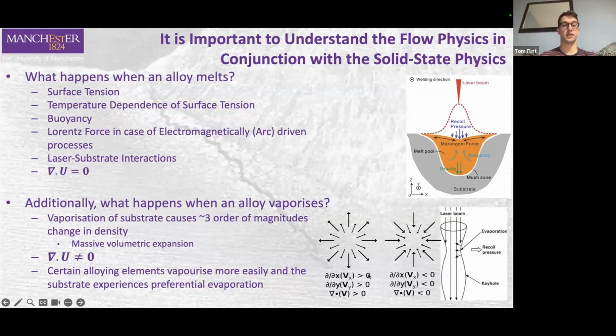So that's more like what we see in this picture here on the lower right hand side. In that case, you would say that the divergence of the velocity field is actually bigger than zero. It's not incompressible anymore. So we did quite a lot of work to develop mathematical frameworks that describe that process while also capturing all of the physics that is kind of universal, whatever your assumption on the velocity field is. The main ones for those are the recoil pressure force and the Marangoni force.